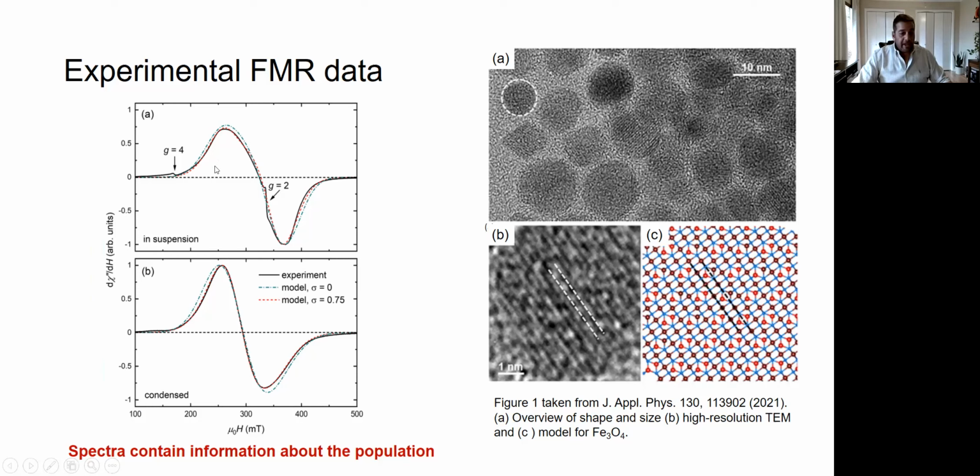And this spectrum here is as we measured it when we received the sample, which was in some liquid form. So the particles were in a liquid, what we call a suspension. This here was after we dried it. So what changed here is only how the particles were turned inside the sample. So you can see a change in the behavior.